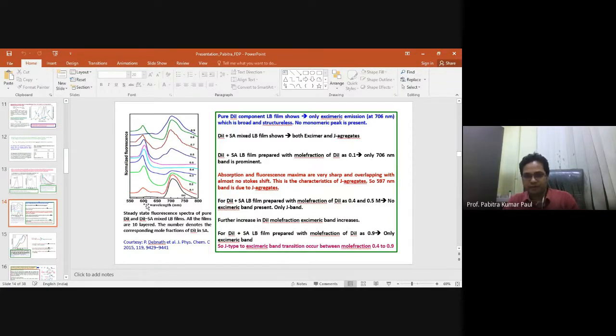So these are the 10 layered films, and the small numbers on the right hand side, I think they are very hard for you to see. This is 0.1, 0.2, 0.3, 0.4 and so on, up to 0.9. These are the mole fractions of the indocarbocyanine compound. In this observation, the pure component, with no stearic acid, shows the excimeric emission at 706 nanometer, designated as an excimeric band, and this band is structureless, very similar to an excimeric emission band.